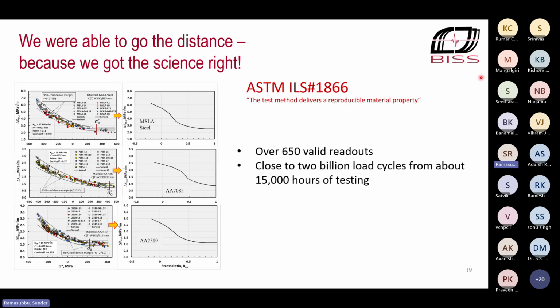So the net result of that interlaboratory study was that we got almost 700 points, which you can see here in a very narrow scatter band of standard deviation of 7% or less on all three materials, 2 aluminum alloys and low alloy steel. Don't forget these were threshold tests. So each data point would take about 2 to 3 million cycles to get. So you can estimate from these number of data points that almost between 15 and 20,000 hours of testing was involved among the 14 labs, which was a tremendous example of outstanding voluntary effort. Nobody got paid for it.